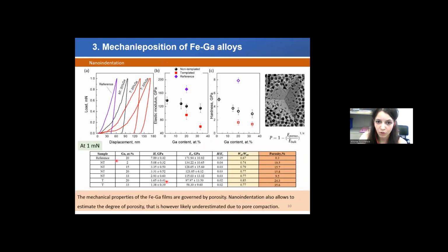The mechanical properties of electrodeposited iron gallium films were studied by nanoindentation technique. So in this slide, we summarized the most important results of this investigation. In this graph, we have the corresponding load-displacement curves recorded on the sputtered reference sample that also had 20 atomic percent of gallium in composition. Again, we focus on 20 and 33% because, according to the literature, this corresponds to the magnetostriction maximum. So the reference sample, then the non-templated iron gallium film grown on the silicon gold flat surface, and the two templated films that were produced using colloidal templates.